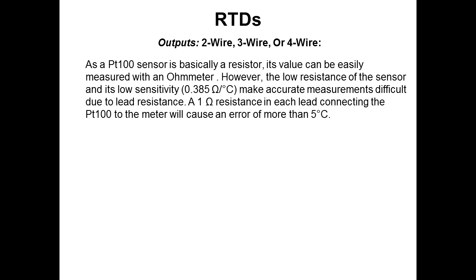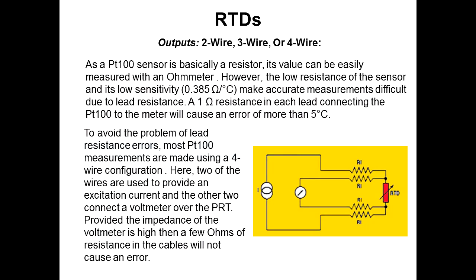So the PT100 sensor is basically a resistor. Its value is measured by an ohm meter. The 385 DIN curve or IEC 751 curve is the most common. There are other sensors that have similar curves. There are 2 American curves that are 392 with a 4th decimal point. That's 2 different ones, which is used in some places, but the 385 is the most common. A 1 ohm resistance in each lead wire, if you don't have these extra wires taking it out, can cause an error of more than 5 degrees C. So the best way is to use the 4-wire, and you want a voltmeter that's high in impedance so that there's a few ohms in resistance. The cables will not cause an error.